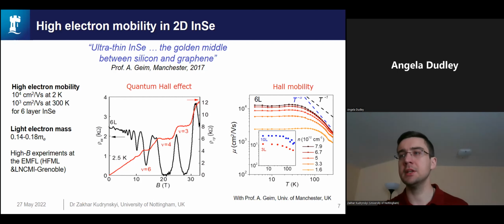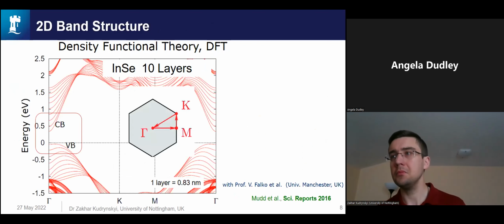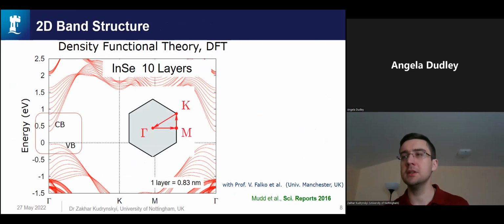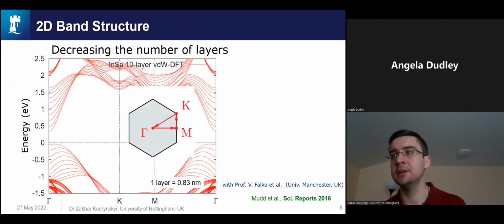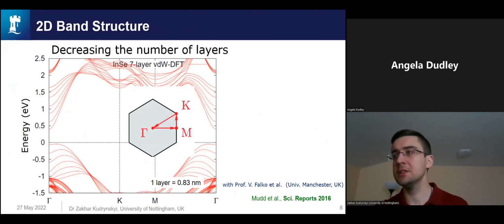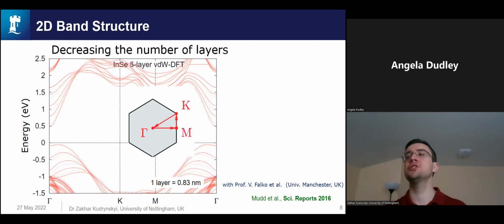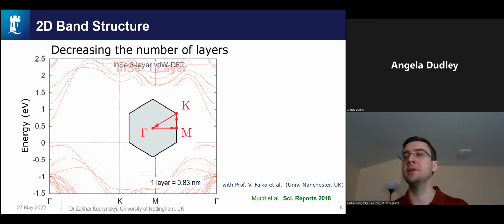And theoretical modeling of the 2D band structure of indium selenide by density functional theory, which was done in collaboration with Professor Vladimir Falko from the University of Manchester, and his colleagues, brought light onto that. So we can start, for example, with 10 layers thickness, and look how the energy dispersion is changing as we make indium selenide thinner and thinner.